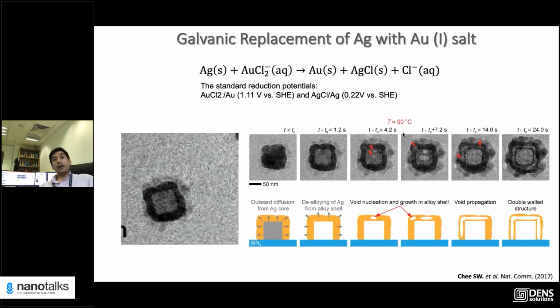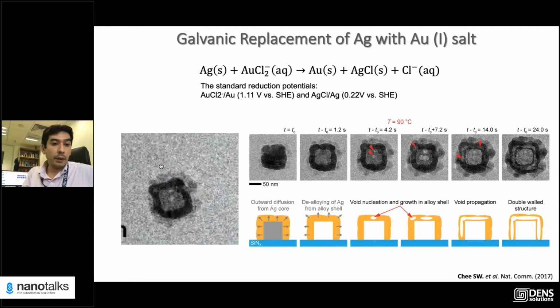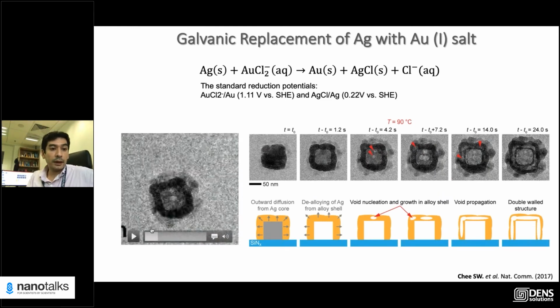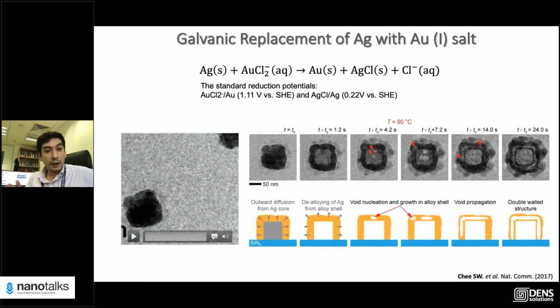Okay, so this was the experiment with the gold 3+, right? So gold chloride 4-. Now, what happens if we use gold chloride 2-, right? So you have now gold 1+. With gold 3+, each gold atom takes away 3 silver atoms. Now, with gold 1+, you only take away 1 silver atom. So you're taking away at a much, much slower rate.